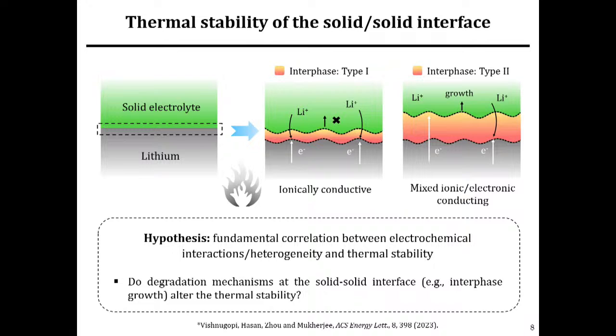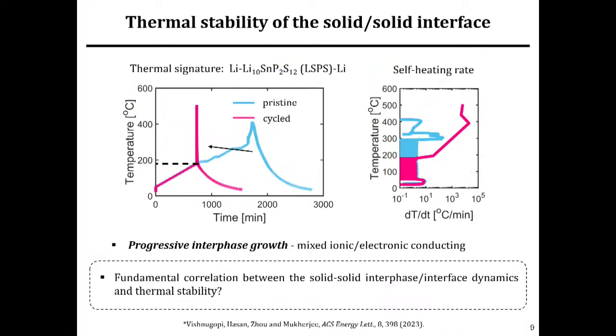Our hypothesis is that there is a fundamental correlation between the electrochemical interactions and heterogeneity at such interfaces with the thermal stability of the solid-state battery. We raised this question in our recent work: whether these degradation mechanisms at the solid-solid interface affect the overall thermal stability of the system. Much to our surprise, the answer was a big yes. This is an exemplar result I'm showing in the case of a superionic solid-state conductor, which is LSPS.